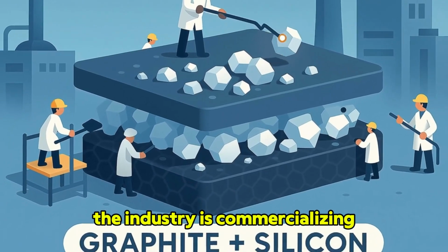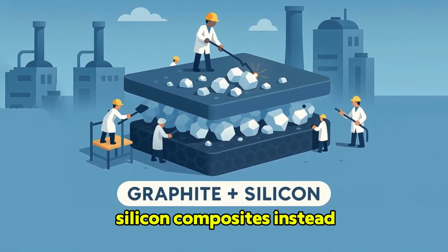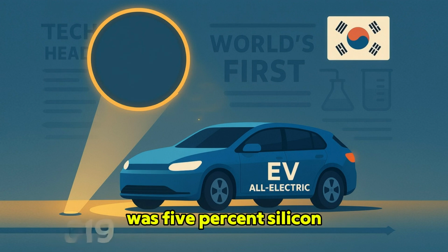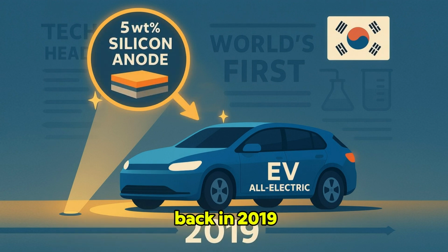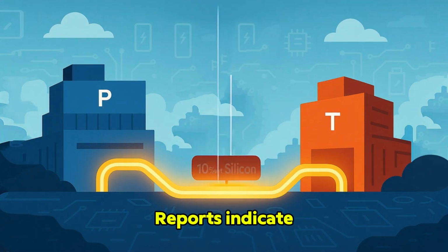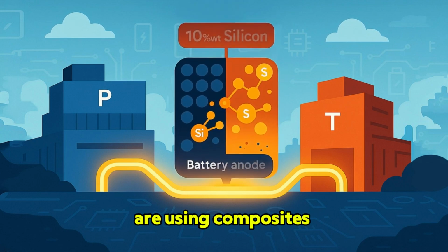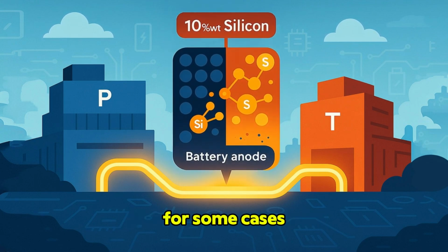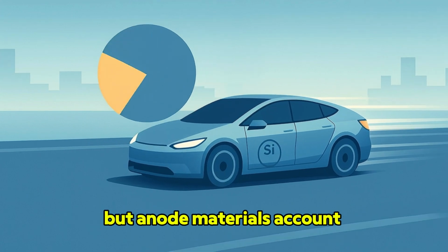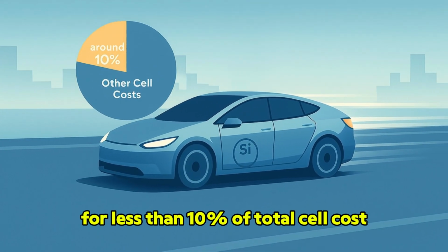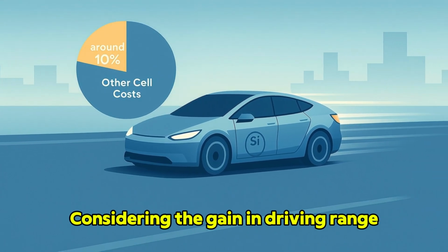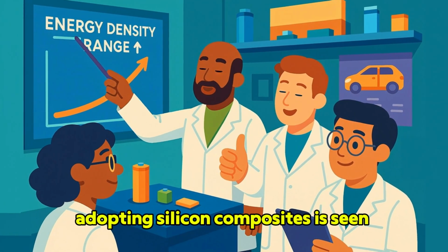This is why the industry is commercializing silicon composites instead. The first real-world mass production use was 5% silicon back in 2019 by LG Energy Solution. Reports indicate Panasonic and Tesla are using composites with about 10% silicon for some cases. Silicon composites are more expensive, but anode materials account for less than 10% of total cell cost. Considering the gain in driving range, adopting silicon composites is seen as highly practical.